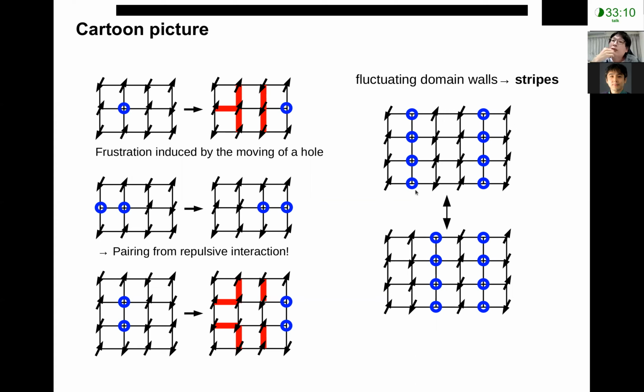So in this way, the system can lower the kinetic energy by moving the holes, but also it would not increase the antiferromagnetic spin energy too much. It's also interesting to see that there's already a kind of pairing mechanism in this picture, that although the Hubbard model is a purely repulsive model, there can be a mechanism where the holes want to go together to recover the antiferromagnetic pattern.